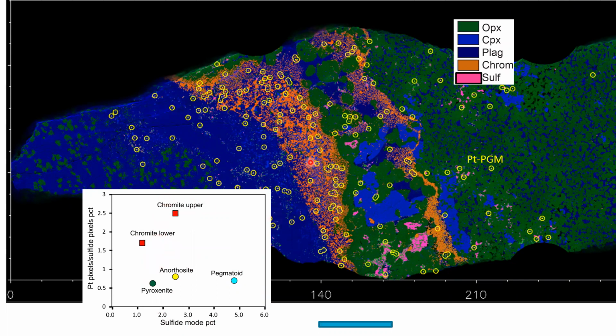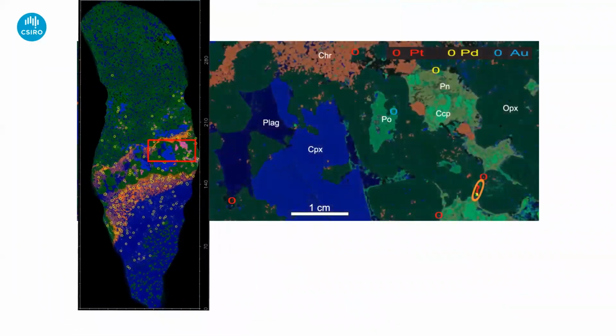So this kind of fits with the idea, an old idea proposed by Tony Naldrett many years ago now, that sulfides in the chromite seam preferentially remelt or disappear as a result of interaction with the chromite. It's a complex mechanism that involves defect structures in the chromite, which I won't try and explain. But that seems to fit very nicely with what we're seeing here. So if we assume that was originally a homogeneous sulfide phase, the sulfide in the chromite seams has systematically redissolved or somehow disappeared and left the platinum behind, which accounts for that change in ratios.